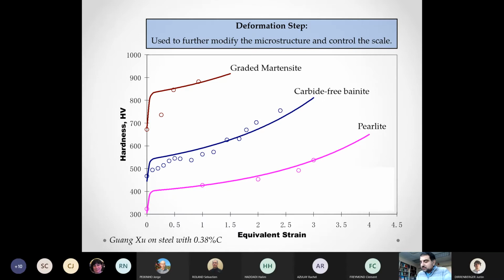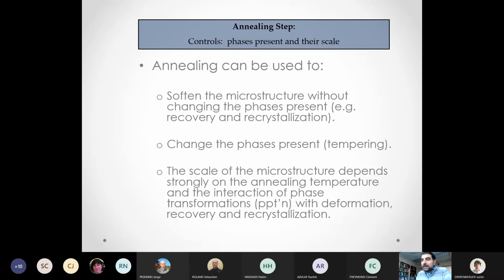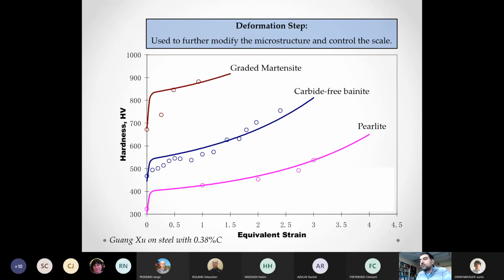And I will show this result later, so I will skip this slide for now. I'll mention that briefly. As I mentioned, we can use our material right away after cooling it to room temperature. Or if we wanted to, we can give it a cold deformation treatment and then anneal it and get new microstructures. And this is one of the most remarkable results we have. This example here is the graded martensite with 0.38% carbon. And we were able to roll this material to a very large strain. The largest strain we were able to get in the lab was about a strain of 2.